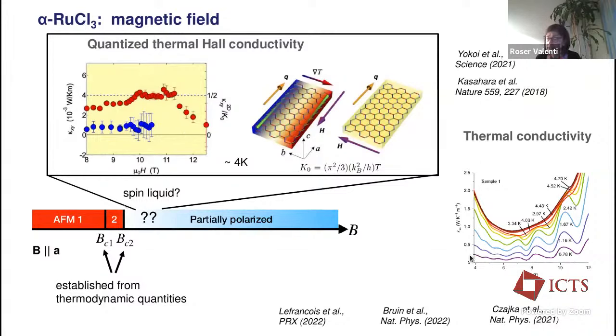In fact, they explain these oscillations in the thermal conductivity as a consequence of having a cascade of phase transitions due to the presence of stacking faults in this system.